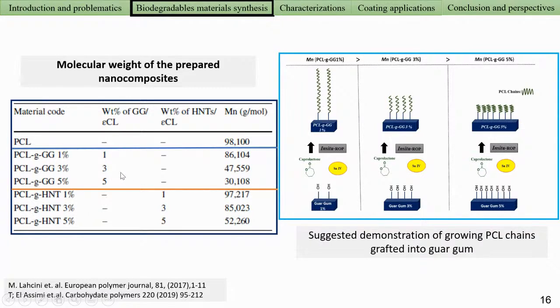But the molar mass decreases by increasing the content of the filler, even with guar-gum or halloysite nanotubes. This is normal because we use the same quantity of monomer. And when we have 1%, like if we have 2 OH groups, so we divide, we have only 2 chains growing on the surface. When we have 3%, we have more chains growing, and when we have 5%, that's the reason why the molar mass decreases.